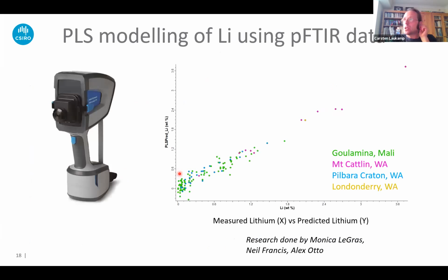As we are talking about lithium, the other reflectance spectroscopic technology to map lithium is this handheld spectrometer, the handheld FTIR. That's mainly work done by Monica LeGras, Neil Francis and Alex Otto, where they collected reflectance spectra with this little toy from a number of deposits in Western Australia, but also from Gulamina in Mali. They calibrated reflectance spectra with the measured lithium content, and they got this correlation, colored up by the different deposits. We can predict the lithium quite well.